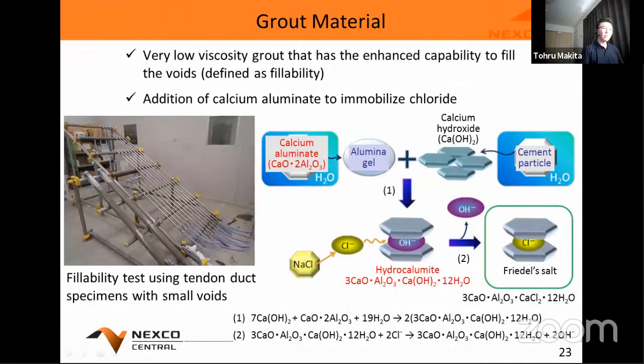Grout material was also improved. The fillability of grout was enhanced by making its viscosity very low. And in order to improve the corrosion protection performance of grout, calcium aluminate was added, which we use for concrete repair material too.